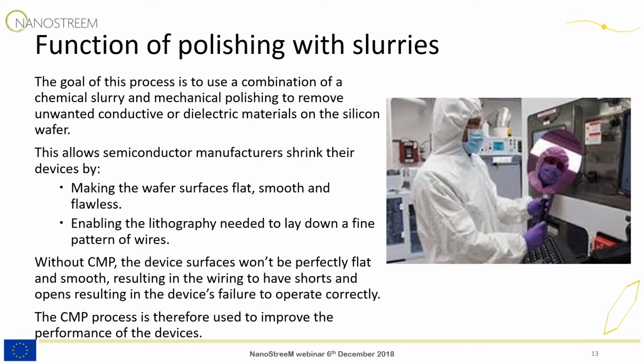Because ultimately, if we didn't do this polishing activity with the use of nanomaterials, the device itself could have the likes of shorts and opens, which ultimately would result in the failure of that device to operate properly. So it is absolutely necessary in terms of the performance of that semiconductor device.